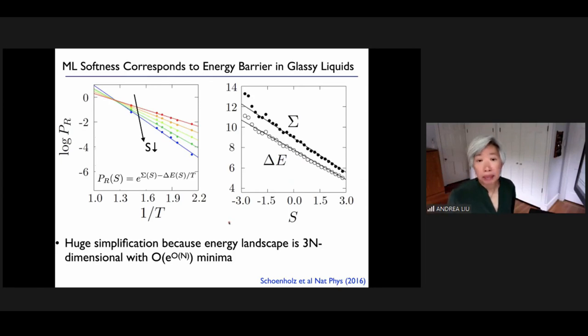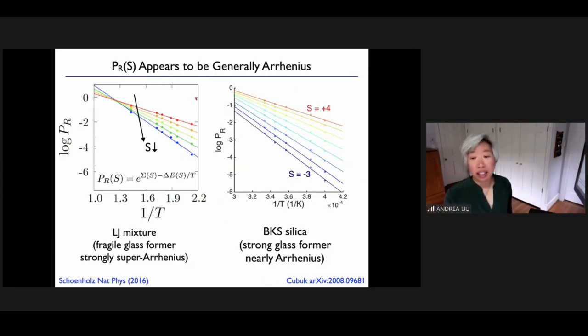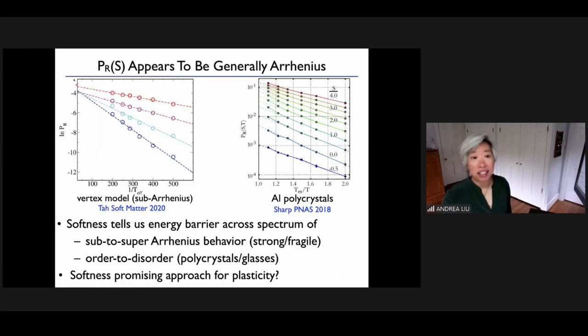Okay, so this is useful, and it turns out to be true for many different systems. So we originally did this for the Kob-Andersen model. It's a Lennard-Jones mixture. It's what's called a fragile glass former with strongly super-Arrhenius behavior. We can also do it for a model of silica, which is what's called a strong glass former. In other words, the relaxation time is nearly Arrhenius with temperature. And not only that, we can do it for other systems. This is the Vertex model of epithelial tissues, but that shows sub-Arrhenius behavior. Again, the probability of rearranging is Arrhenius, in this case for cells of a given softness.